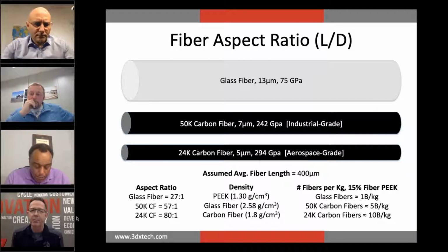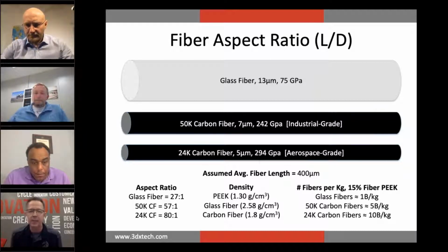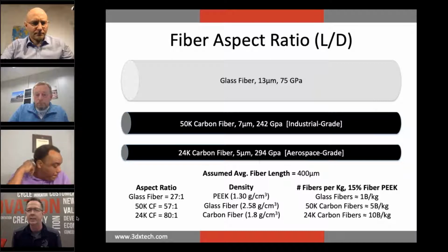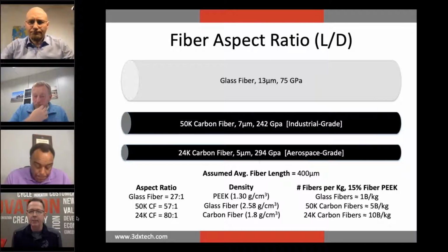But if somebody says, hey, you're using 15% carbon fiber filled PEEK, some of this has to do with not just the percentage of carbon fiber that you're using, but also which type of carbon fiber. So if you're using a stiffer carbon fiber, such as the 24K intermediate modulus aerospace grade, versus somebody else using an industrial grade 50K.